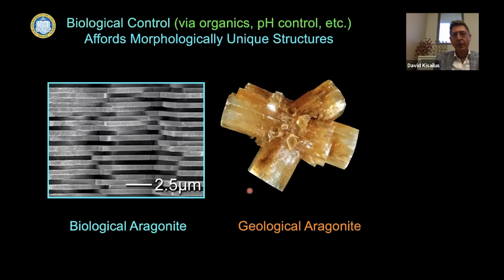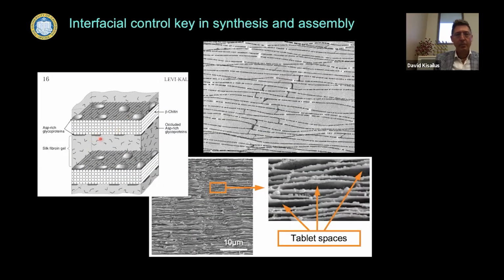And so often, if we take a look, for example, at the nacre, it's made of aragonite. And if you look at geologic aragonite, it typically tends to form needle-like structures. So why and how does nature control this to form hexagonal-like tablets with controlled thickness? This is some work by Levi-Kalisman that shows the underlying organic scaffold of beta chitin, which are polysaccharides that are often co-associated with proteins. And those proteins contain domains that act as, if you will, sinks to enhance nucleation and create supersaturation in microenvironments.